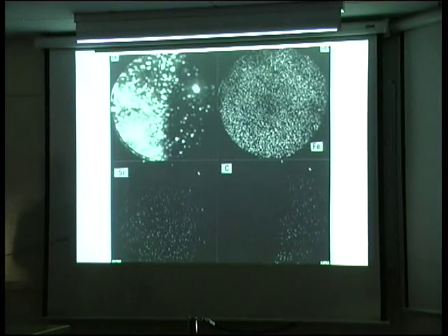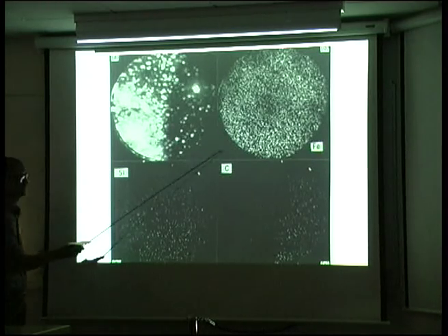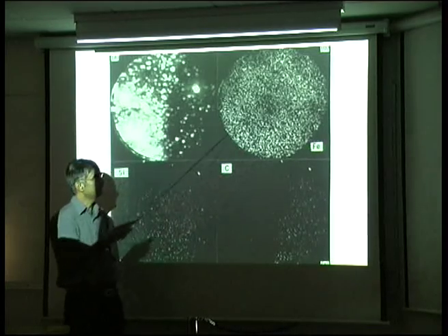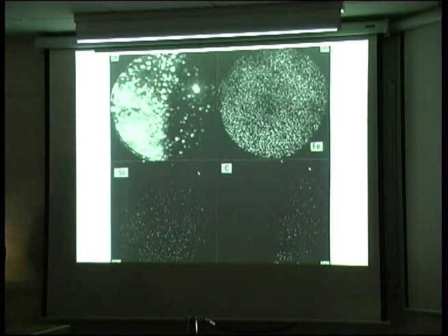Yeah, great, thank you. Now each dot here is a single atom. So we are doing both position analysis and chemical analysis on the finest conceivable resolution that you can have. And this is a field ion microscope image. We can, using this technique, pull out individual atoms and measure how long they take to fly between two points, so that's time of flight mass spectrometry, and determine their chemical composition. And we can capture particular species of atoms and form an image. So this is the distribution of iron atoms. You can see it's uniform. This is the distribution of silicon atoms. And you can see that it's uniform. So we can conclude that substitutional solutes do not partition between the phases, even on the finest conceivable scale.